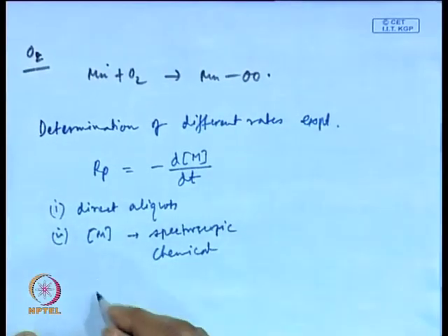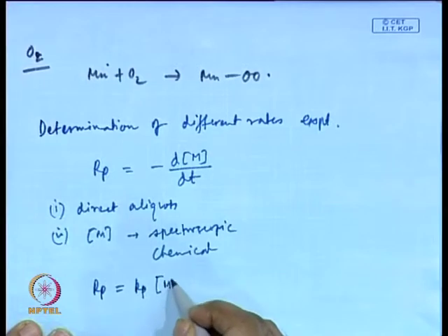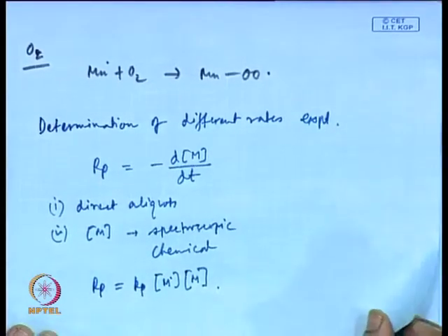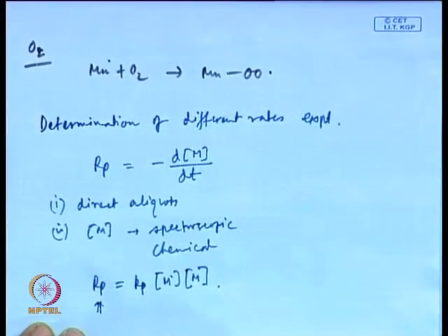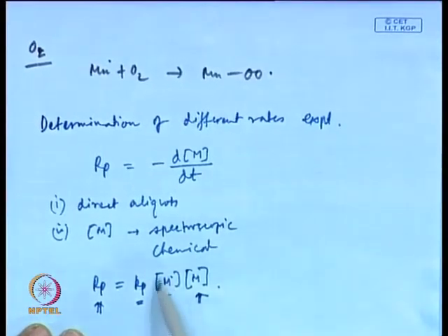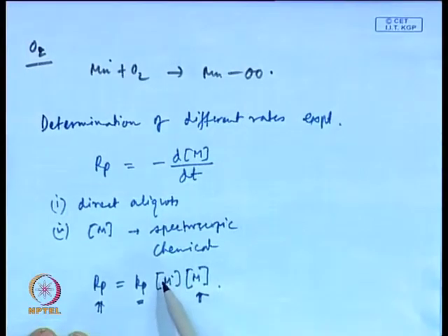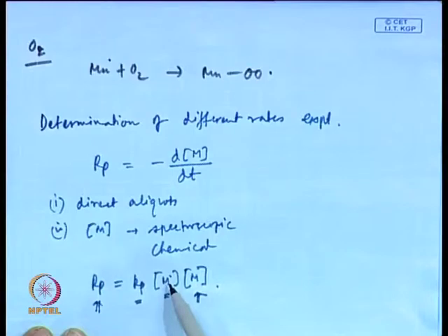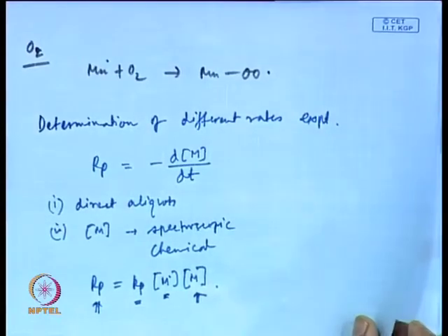Now, we get it once more, this is the expression for Kp, just as a reminder. So, we know this now from the experiment, and we can find out the concentration of M as well. So, this Kp and M dot are the two unknown quantities. Now, this M dot, in theory or in principle, can be found out directly from ESR measurements, which can give the total radical concentration, especially at the steady state, but because the lifetime of these radicals is very small, normal ESR technique is not very accurate to find out the value of M dot. So, ESR does not give very accurate results for the M dot value.